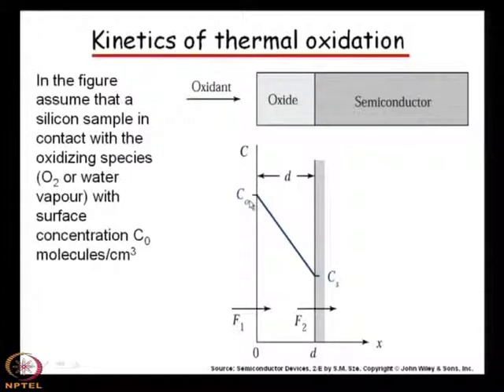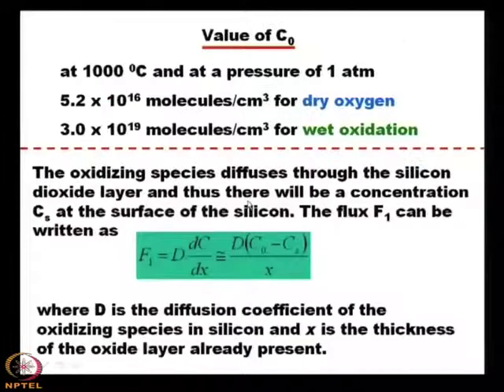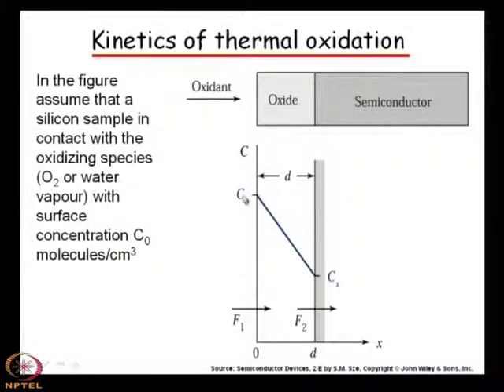So, the next step is, what is the value of this C0? The value of C0 for dry oxygen is 5.2 into 10 to the power 16 molecules per centimeter cube, and for wet oxidation its value is higher, 3 into 10 to the power 19 molecules per centimeter cube. It is at 1000 degree centigrade and at a pressure of 1 atmosphere. Now, if you change the process condition, suppose you increase or decrease the temperature, or increase or decrease the pressure, the values will change. So, this is the value of C0, which we have assumed to be the concentration at the surface.